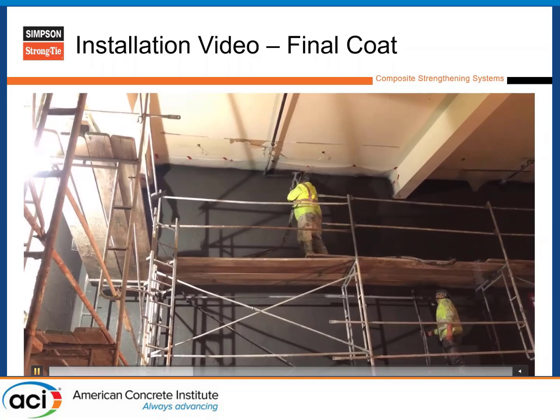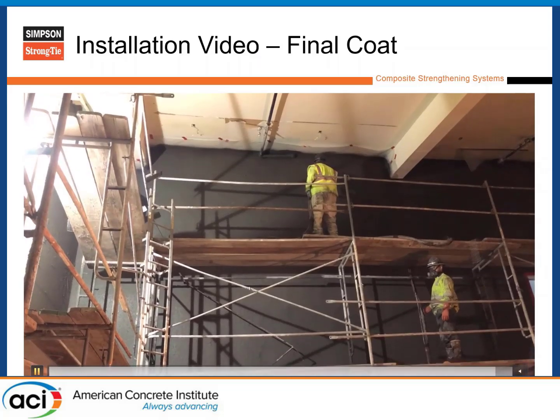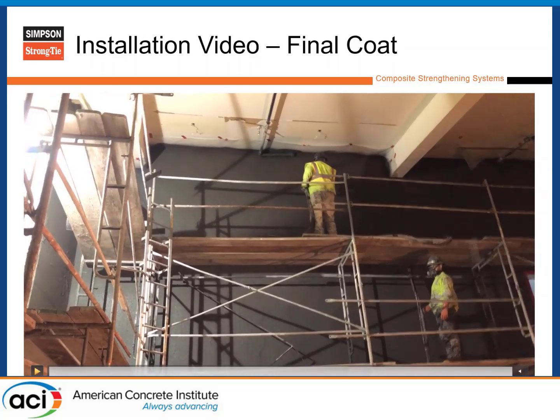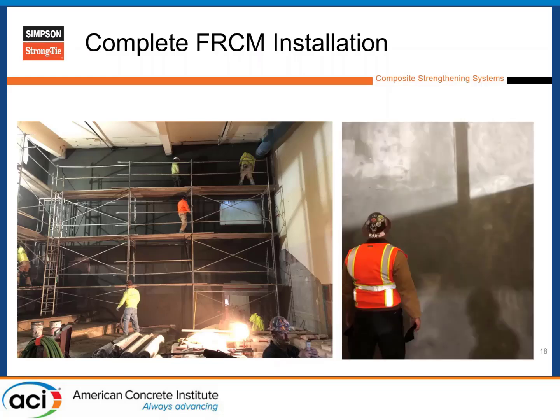The grid has been laid out — it's about 77 inches wide on a wall about 25 feet tall. An additional quarter inch is sprayed over the top to seal the whole system. We don't have cover requirements with carbon fiber grid, so half inch is the actual thickness of the installation. They did this entire room in about three hours. The photo on the right shows the system right after finishing spraying — they hit it with a wet sponge for a smooth finish. As it dries out, it looks almost like a stucco or plaster finish, just with a slightly heavier grit in the mix design.